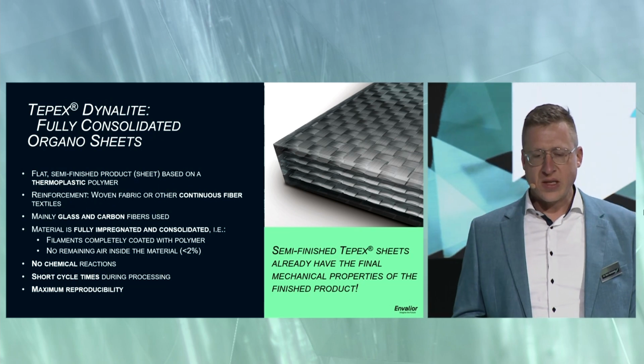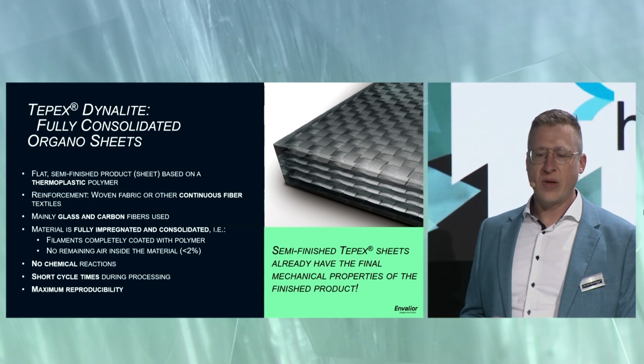So what is important about Tepex, and what differs us maybe a little bit from some competing materials, is that Tepex is more or less fully consolidated and impregnated. Thus, there are no voids, let's say voids in a range of less than 2% in this material. So it's very compact, and it's really important to get the highly viscous thermoplastic resin very close to the fibers, so you have the perfect adherence between the fibers and the matrix material.